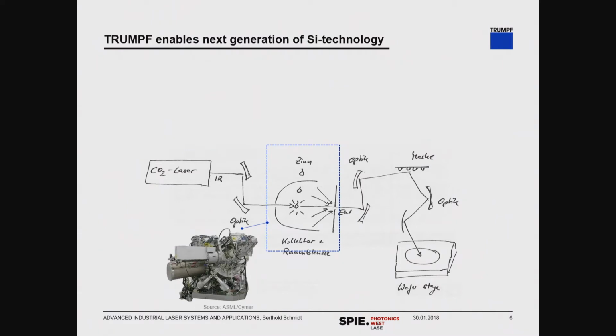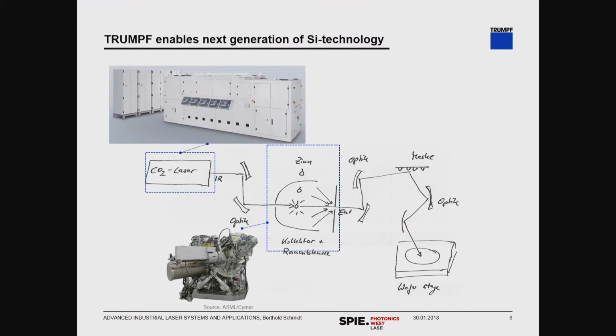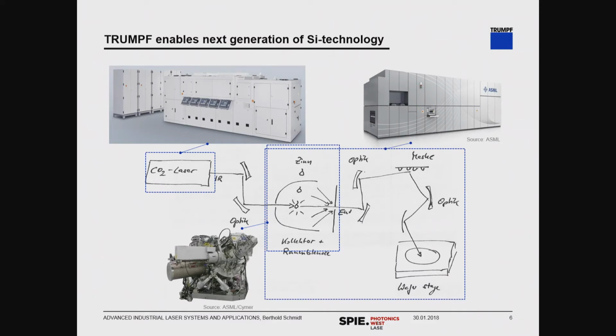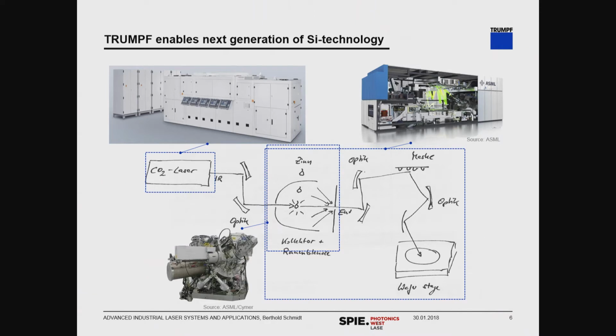The droplet generator that is used is already a technical challenge, creating 50,000 droplets per second, so we have to hit each droplet with a frequency of 50 kilohertz. Actually, we have to hit it twice. First, there's a pre-pulse, and we create a small mist of particles. And then with a second pulse from our lasers, which already has the size of a house, a diffraction-limited laser, we create this plasma. And then the lithography system, which unfortunately normally stays in these fabs on the top, with our lasers in the basement, has roughly the same size, guiding the EUV light onto the mask.